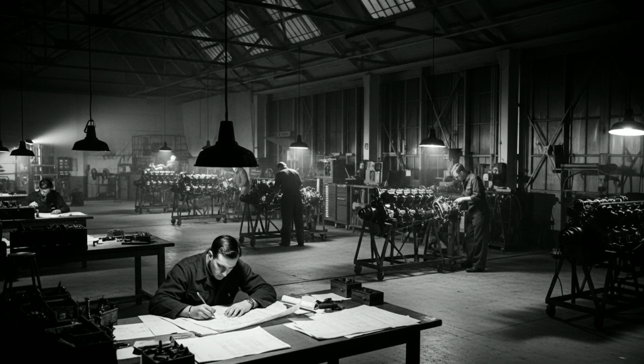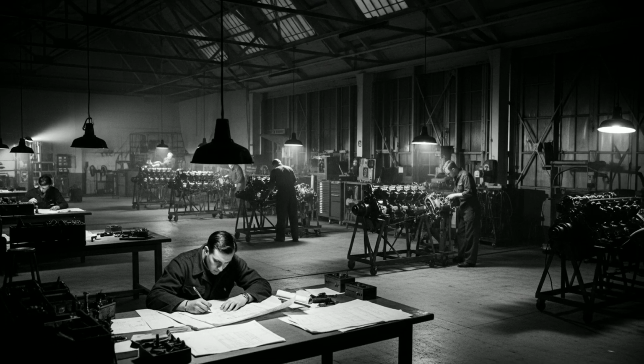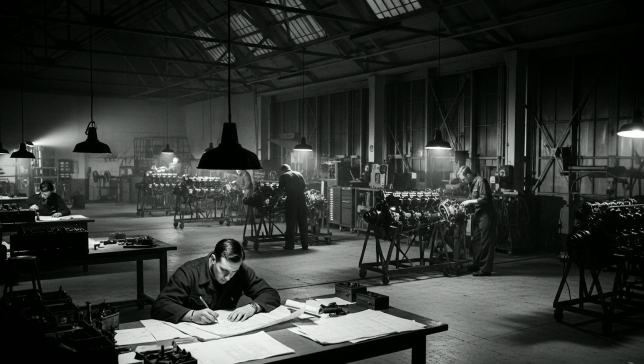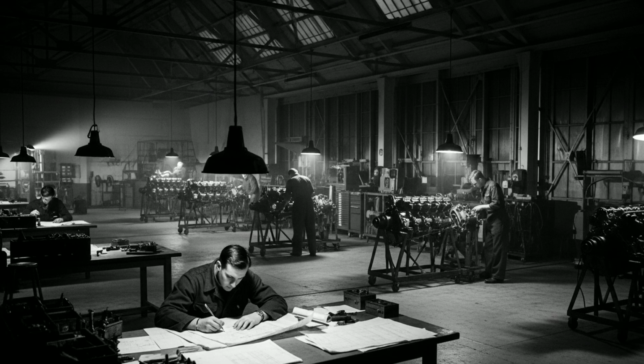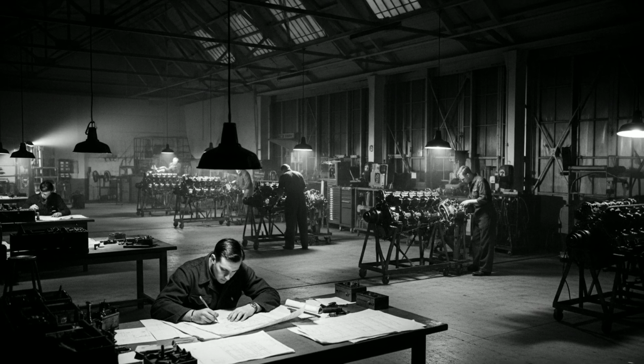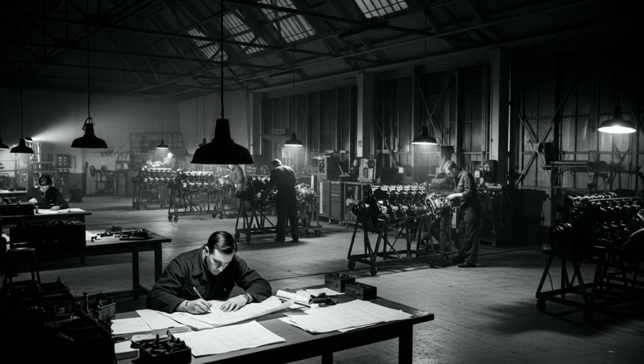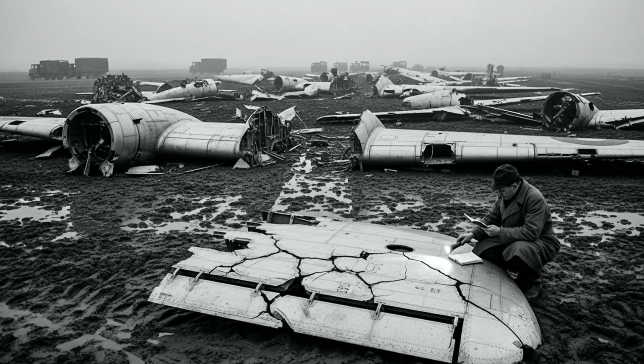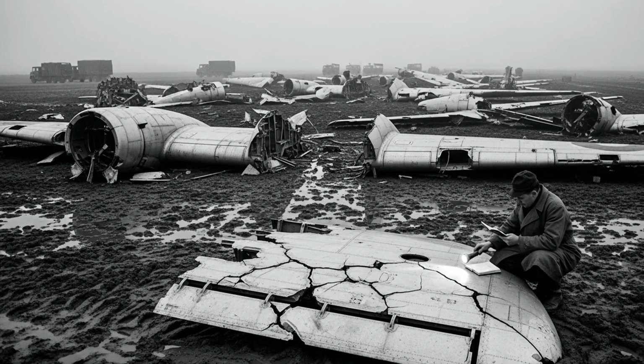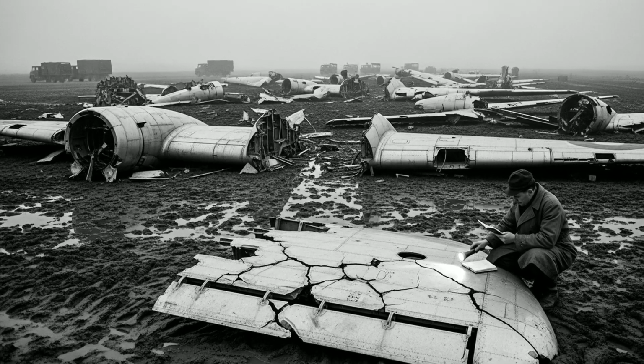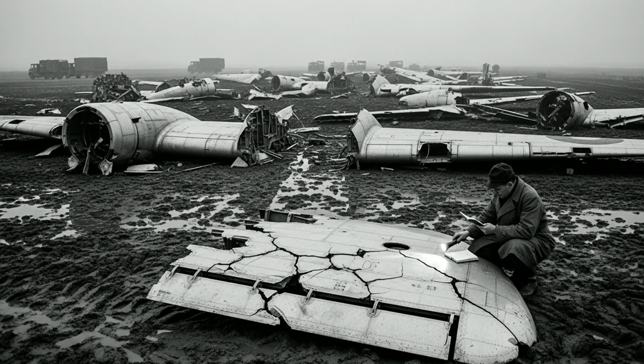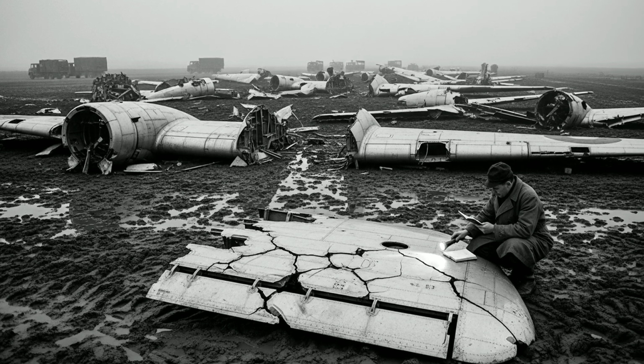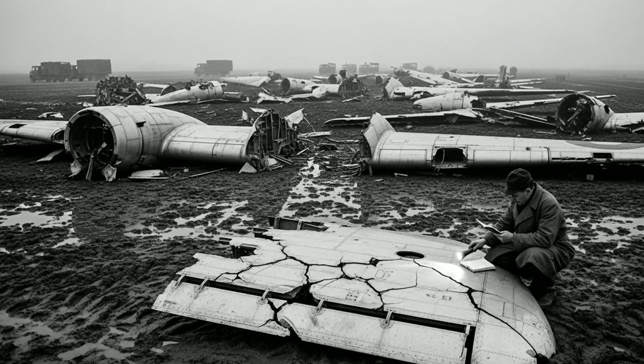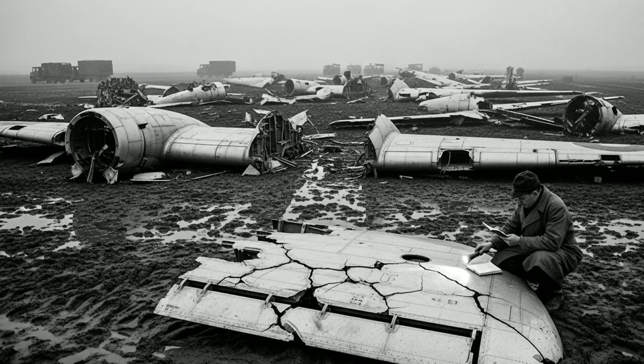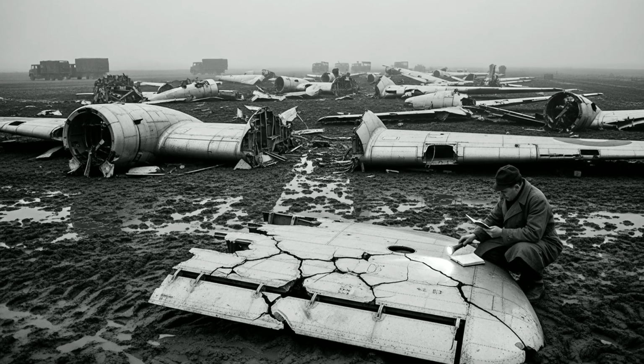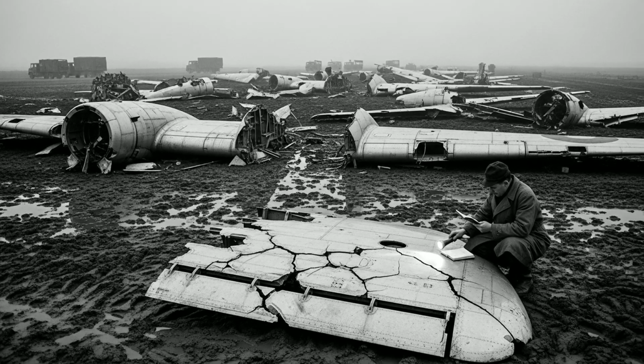The second wing came from a Liberator that had broken apart over the North Sea in January. The aircraft had been returning from a mission to Hanover, severely damaged by flak, when both wings folded simultaneously at altitude. No survivors, only fragments recovered. The spar fracture was identical. Same location, roughly 80 inches from the root. Same fatigue pattern. The third wing, the fourth, the fifth. Every single failure occurred between 75 and 90 inches from the wing root.